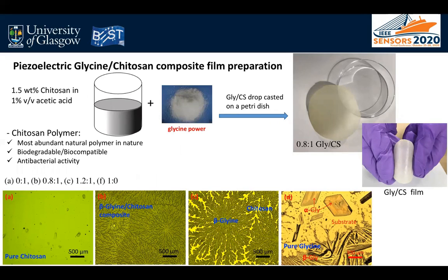For this, first we prepared a 1.5 percent chitosan solution in 1% acetic acid solution, and then a series of glycine to chitosan composite solutions were prepared by dissolving different amounts of glycine powder in the prepared chitosan solution by stirring, and then the solution was cast in a petri dish, and through an evaporation technique we could have a flexible film.